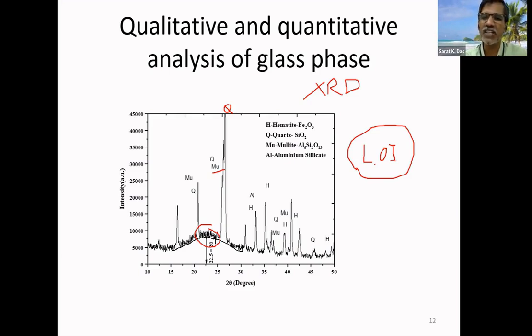Before 2000, there was a restriction on LOI up to 12%. But then this was creating a hurdle; I'll tell you later how it is going to affect my geotechnical properties and other properties. So then the stipulation or the mandate came that it cannot be more than 2%. And nowadays, people are getting even less loss on ignition because the plant efficiency is increasing. Because the loss on ignition depends upon the efficiency of the plant, and this aspect is not in the ASTM standard. It is simply mentioned as the limit, but its impact is more, and I'll show you later some of its impact. So loss on ignition is nothing but your unburnt carbon.